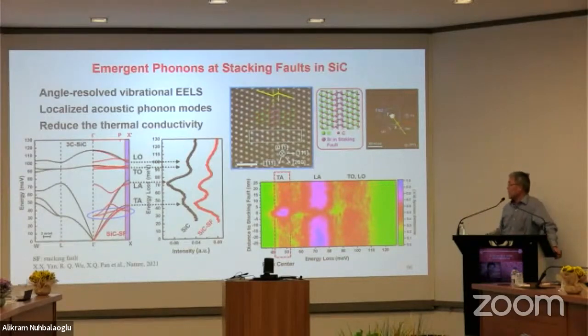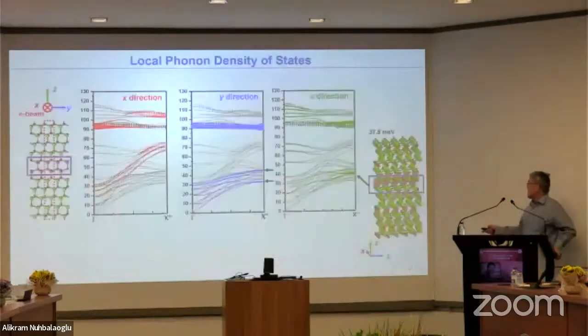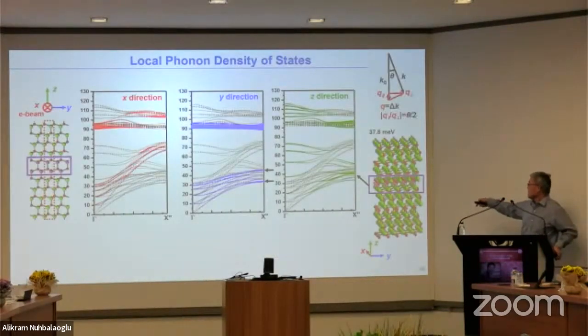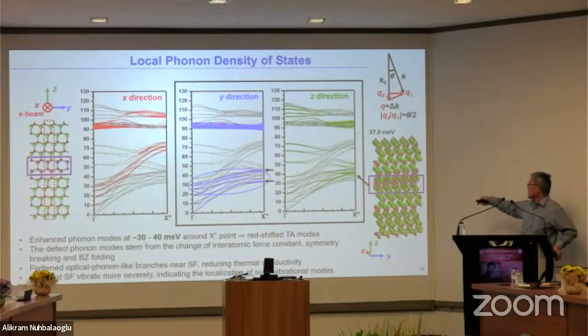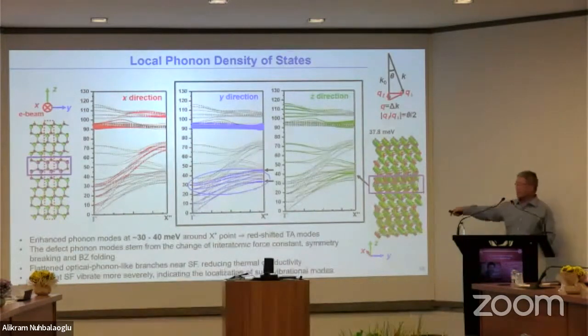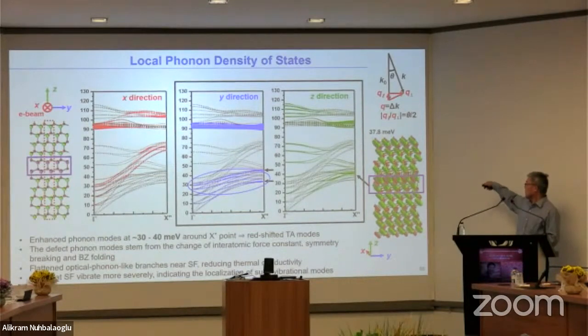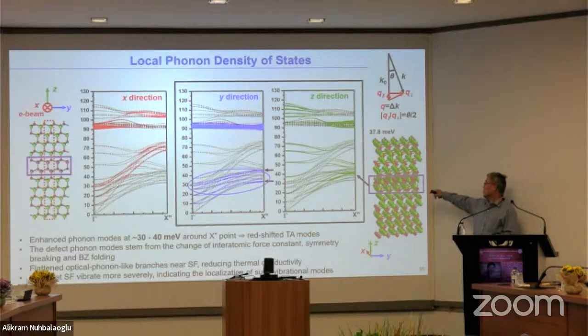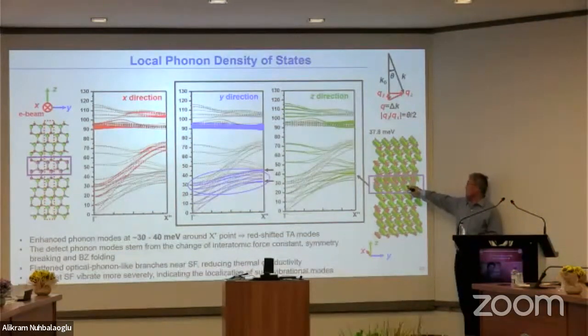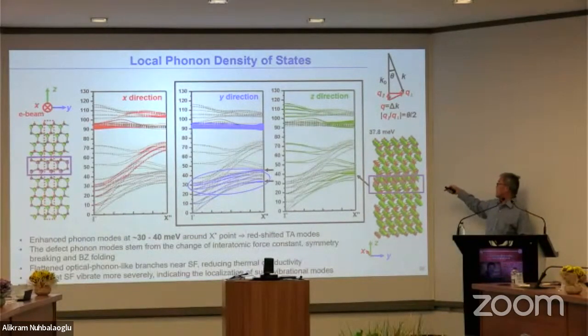What is energy shift and what is what. But to demonstrate the mechanism, I just want to use this theoretical observation by Professor Wu and build the model with a silicon carbide. This is a single stacking fault. You can see here atomic scattering in this stacking fault region. The amplitude and also the angle of bonding are different from the bulk.